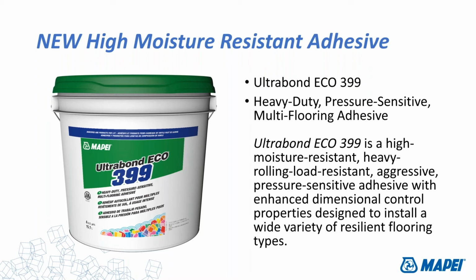I'm not telling you that you can install LVT in an unacclimated environment and think that the adhesive is going to solve all your problems. You still need to follow all the rules. LVT and resilient flooring should be installed in the environment and the ambient temperature conditions in which the building is going to be maintained. Ideally, you should be installing flooring at 72 to 75 degrees Fahrenheit, and not bringing it in from the cold and installing it all nice and tight and then turning the heaters on. That's not going to be a good solution for any kind of flooring. So 399 is going to help you control some of the gapping that might occur with normal shrinkage of LVT.